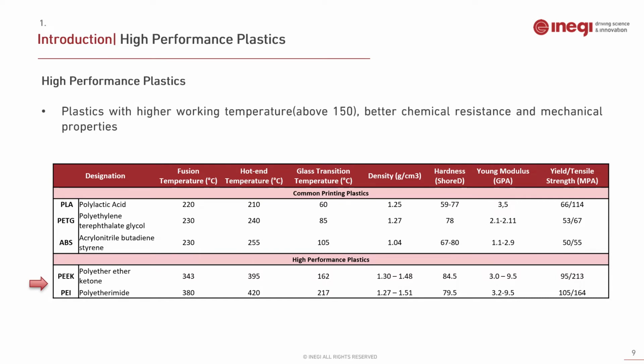For this work, we have chosen to use PEEK and PEI as a reference for high-performance thermoplastics due to their higher availability. And, as seen in the presented table, we can see that both these materials have higher glass transition temperature and consequently higher printing temperatures, along with higher Young's modulus and yield and tensile strength when compared to standard materials.